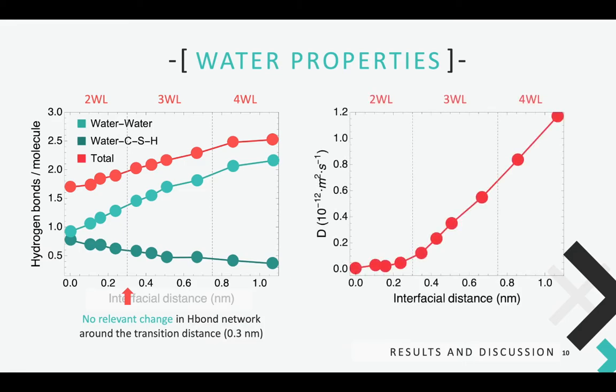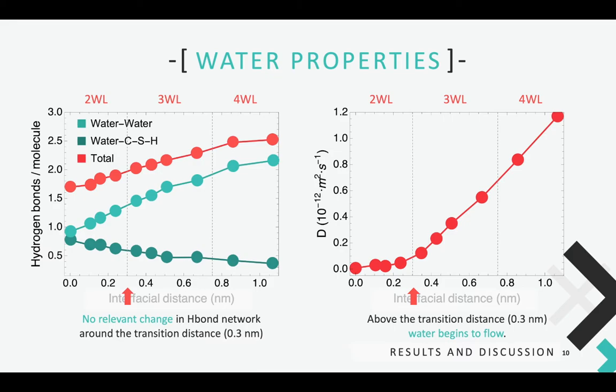We have also determined the diffusion coefficient of water molecules as a function of the interfacial distances. The diffusivity of water molecules is very low below 0.3 nanometers, but above that distance water begins to flow and the average diffusion coefficient increases linearly with the interfacial distance. This change of diffusivity at 0.3 nanometers coincides with the loss of cohesion and the interfacial distance at which the bilayer evolves to a water trilayer. Therefore, we can attribute this behavior to water molecules that are no longer directly coordinated to the CSH surface and start to behave like bulk water, displaying increased diffusivity and causing the sharp reduction in shear strength and energy barrier.